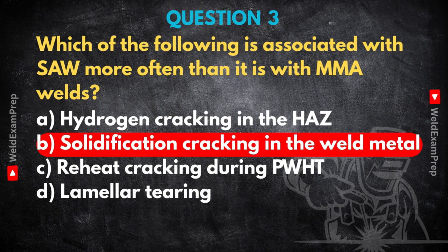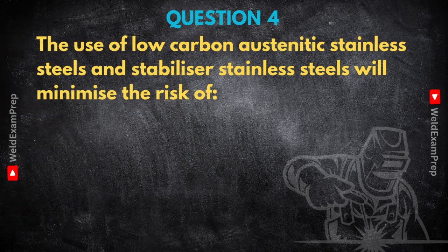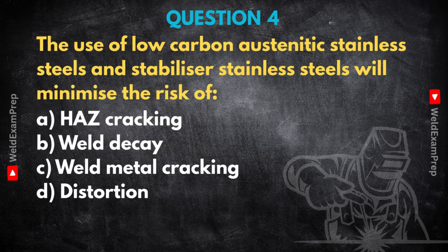Makes perfect sense. Okay, let's switch to materials. How clever material choices can head off serious problems. Think about certain types of stainless steel specifically. Low carbon austenitic grades, and also stabilized stainless steels. When we deliberately choose these materials for a job, what major risk are we primarily trying to minimize? Is it HAZ cracking? Is it something called weld decay? Weld metal cracking? Or maybe distortion? With those specific types of stainless steel, the low carbon or the stabilized grades, the primary target we're aiming to prevent is weld decay.